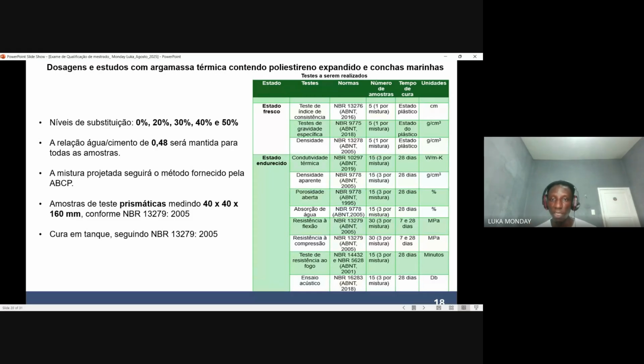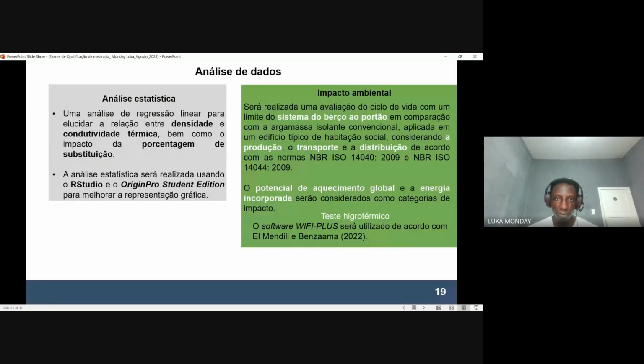With respect to the various tests, the tests to be performed include the fresh tests, the consistency index test, the specific gravity test, the density test, the thermal conductivity test, the apparent density, the open porosity, the water absorption, the flexural strength, the compressive strength, the fire resistance test, then the acoustic test, to test the response of this material with respect to fire and sound as an insulation material.